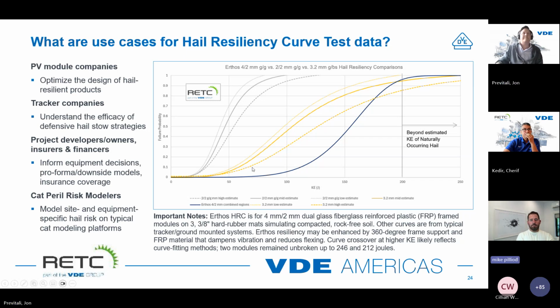I just think from a population perspective, if you take the gray line and you look at the kinetic energy and then the probability of failure, when you compare those to even the yellow or the blue line, at say like 100 joules at that section, that's where you're seeing a very high statistical difference in the population, especially for the Erthos module. You're below 0.1% or 10% of the population that's going to break under those energies predicted. In the 2.2 glass, you're upwards of 100% of the modules.